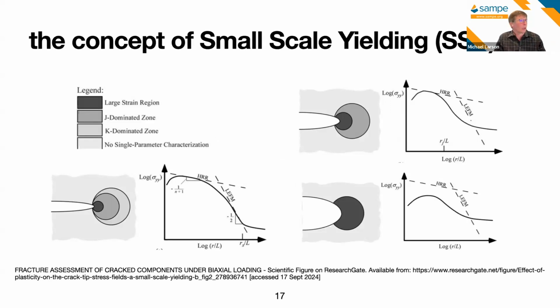We do appeal to this idea of small scale yielding, and this on interfaces is something that has been covered by lots of the giants in the development of fracture mechanics. And here is a figure that I lifted that is royalty free, and the reference you can find there. I thought it was a nice figure from someone's dissertation reminding us what we mean by this. In the legend, it shows areas around a crack tip that correspond to a large strain region, a J-dominated zone, a K-dominated zone, and then a no single parameter description.